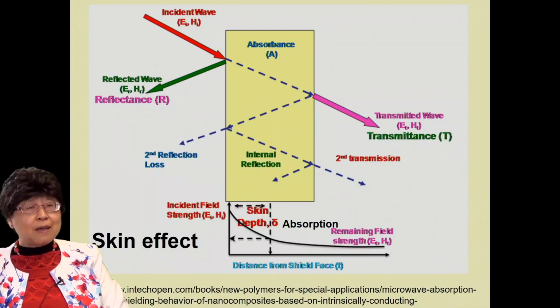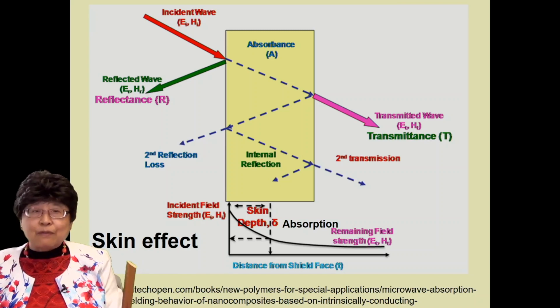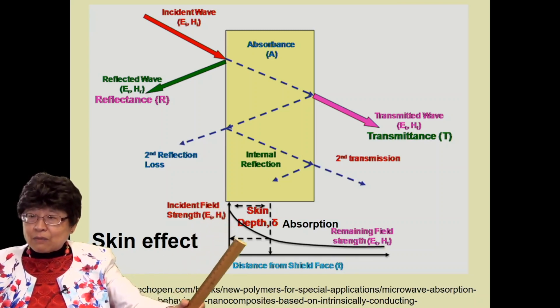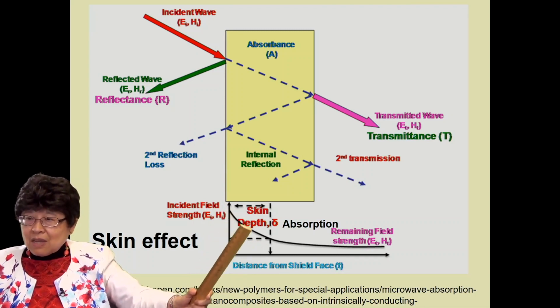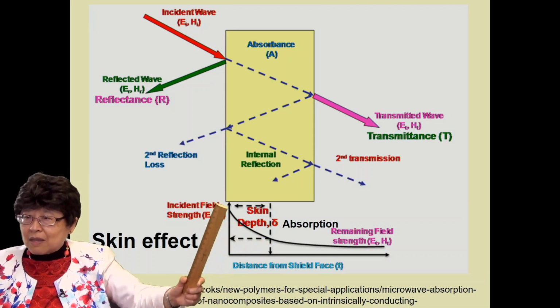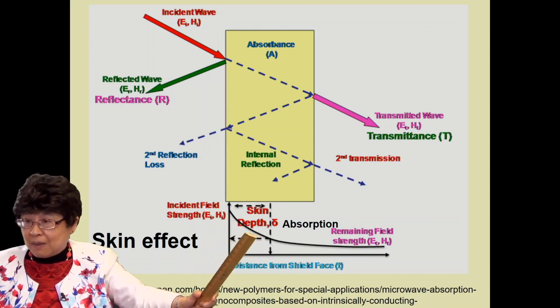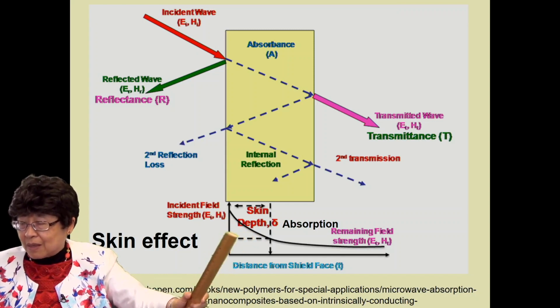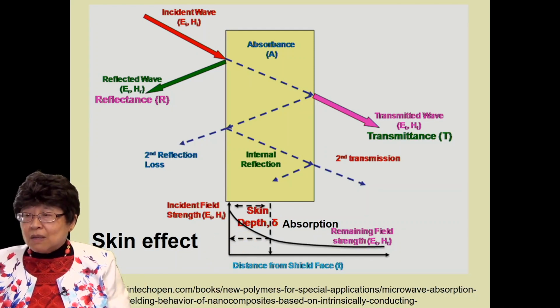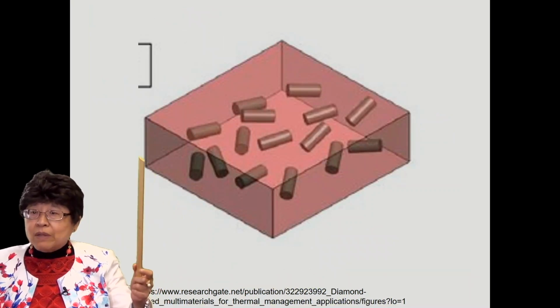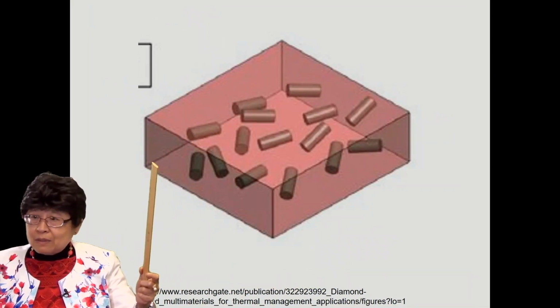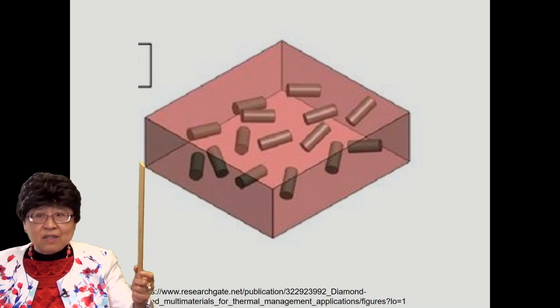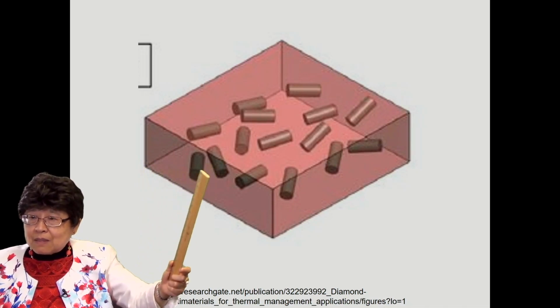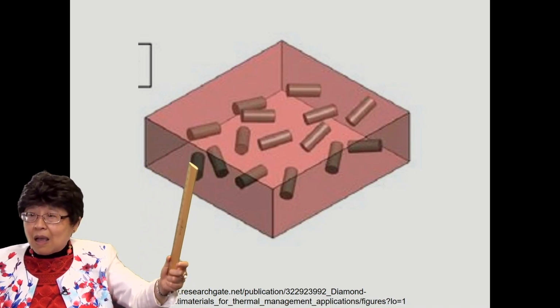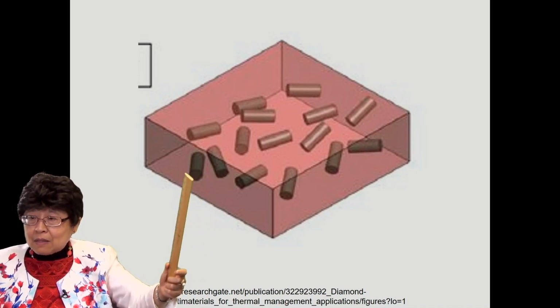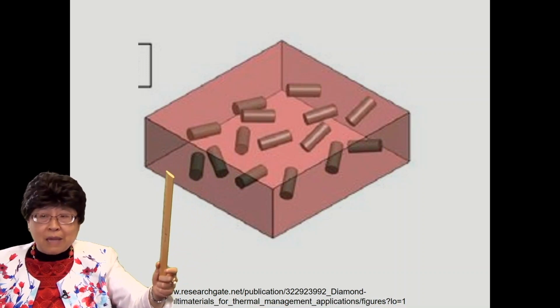Why the surface area or interface area matters is because of the skin effect, which means that the electromagnetic radiation can penetrate the conductor to only a limited degree, so that the electric field decays exponentially as it goes into the material. And so if you have a composite with the matrix being a polymer or cement, which is not very good in shielding, and you have some fillers which are conductive, you have an interface between the filler and the matrix.